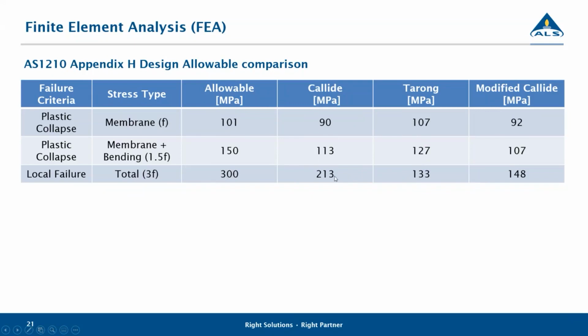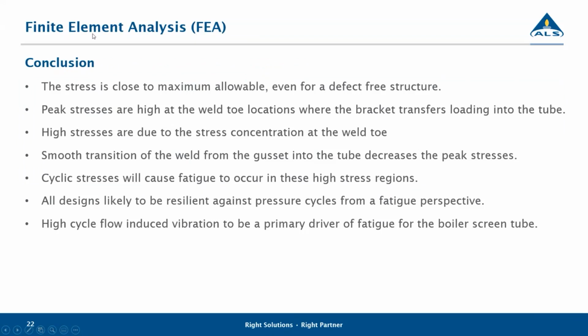So the peak stresses were quite significantly different because that weld is blended in, and this one has that abrupt stop. So we basically cut back that bracket and put a weld on top of it and blended it out to drop the peak stress. And that's pretty much what we could do with the geometry on the plant. So from the FEA side, the stress is close to the maximum allowable, even for a defect-free structure. So that means when they designed the sling tube, just from a pressure perspective even, we did the code calcs as well, they had that very highly loaded. So that's not even considering the bracket geometry.